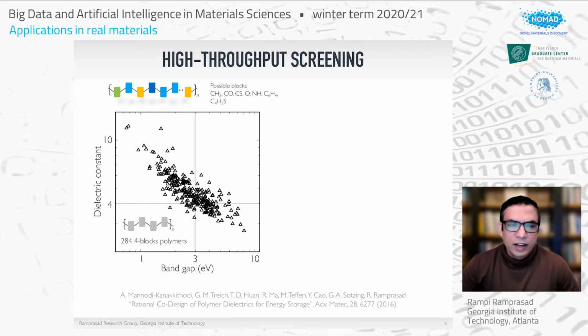So we were initially dejected. We thought, what do we do? You see polyethylene, polypropylene down here, large band gap and low dielectric constant. And if you go to the other end of the spectrum, you have the conducting polymers, low band gap and high dielectric constant. Most of the dielectric response comes from electronic response. So those are the common conducting polymers. But for this application, we want high dielectric constant, high band gap.